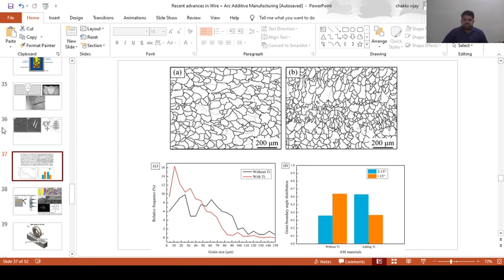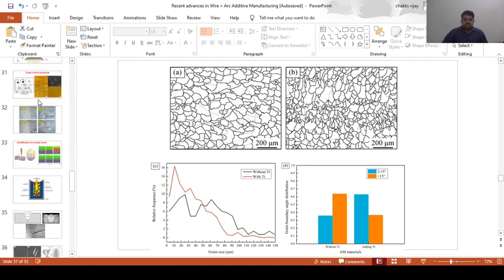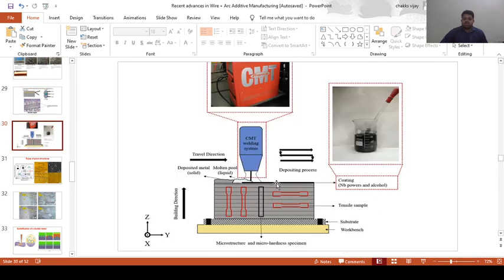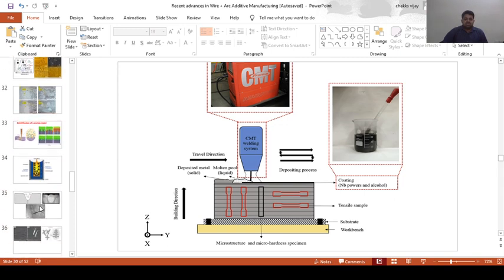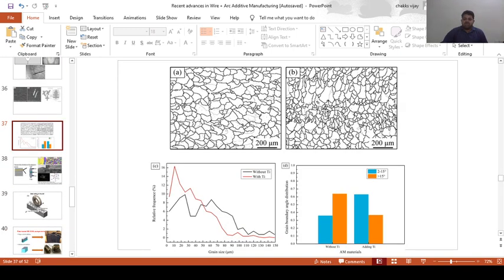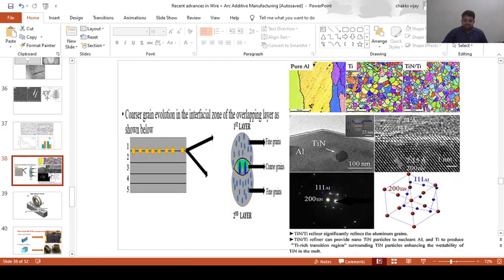So after depositing each and every layer, if you deposit this titanium layer, then obviously the interfacial zone will have finely refined grains. That is one of the key advantageous features. Titanium is one of the most potent grain refiners, as I told you earlier. So it is pure aluminium. If you add a small quantity, like 1% or 2% of titanium, then all the coarser grains get refined into finer grains.